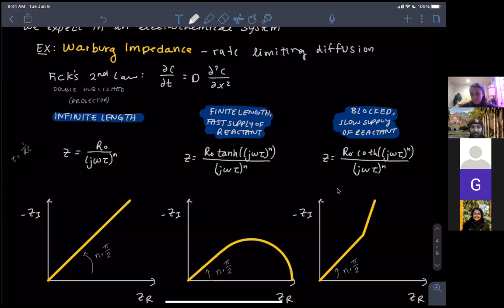To add on to that, Fick's second law is usually purely concentration-driven diffusion. If you're applying a bias across, say, point A to point B, you also have to consider the drop in electric potential, and that will affect the electrochemical potential of, say, the lithium ion. Now you have to consider how the electrical potential is distributed across the media you're talking about. That's a really complicated PDE to solve. Thanks, Alan.